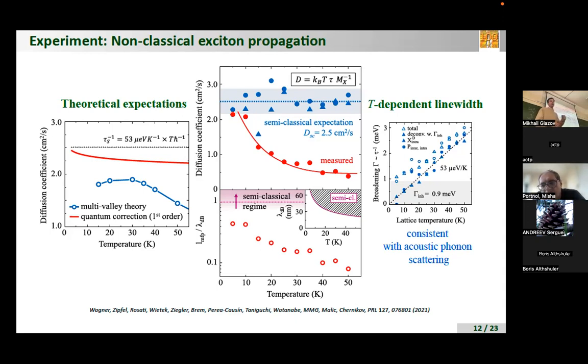Importantly, spin or pseudo-spin of excitons can affect the interference, similarly to the case of electrons. The situation is, however, a bit different. Electrons are fermions, and for closed trajectories, if the spin-orbit interaction is present, the Berry phase is pi, and that is why you change from weak localization to weak anti-localization. That's a very strong signature of spin-orbit interaction, and you can observe it in many cases. You can evaluate Rashba-Dresselhaus terms in this way.